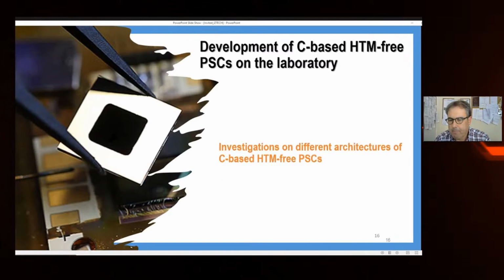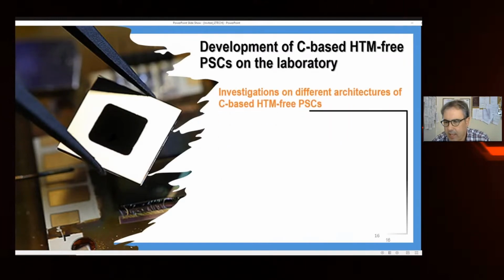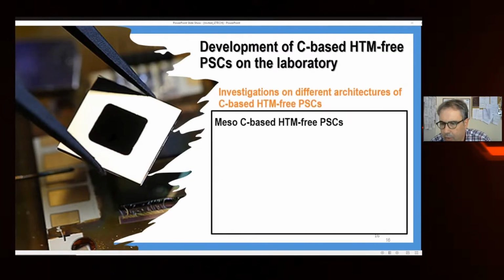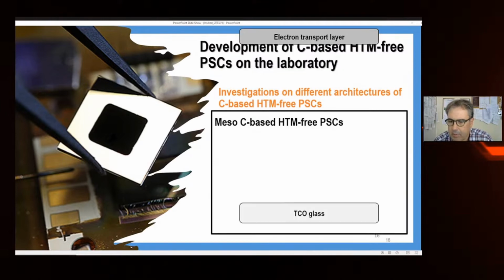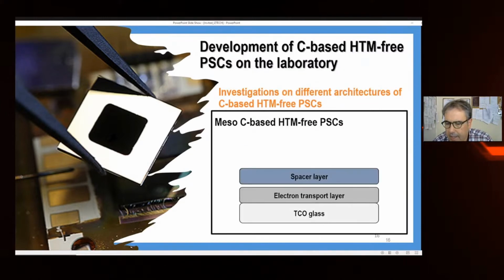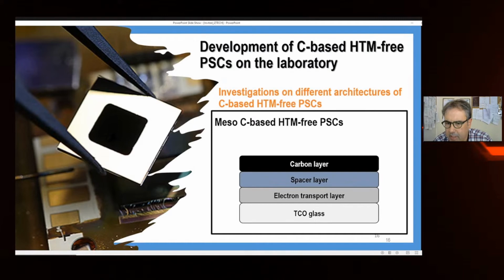So, what is the basic structure that we can follow with carbon? With carbon, the first one is what I said before: the mesostructure carbon-based HTM-free perovskite solar cells. As I said, we have titanium dioxide here, alumina here as a spacer and insulator, so as not to have short circuits between the carbon and the electron transport layer.